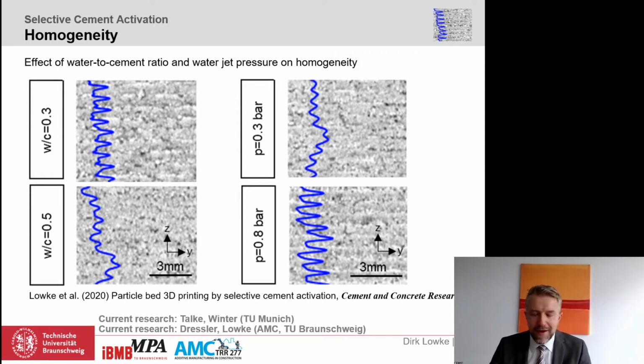If you're interested, please have a closer look at our paper in the recent special issue of Cement and Concrete Research. What you can see here is the effect of water-cement ratio as well as the effect of water jet pressure at the nozzle on the homogeneity of our specimens. We can see that with increasing water-cement ratio or decreasing water jet pressure, the homogeneity of the specimen significantly increases. This graphic should demonstrate that we are able to control the homogeneity by means of concrete technology or process technology parameters.